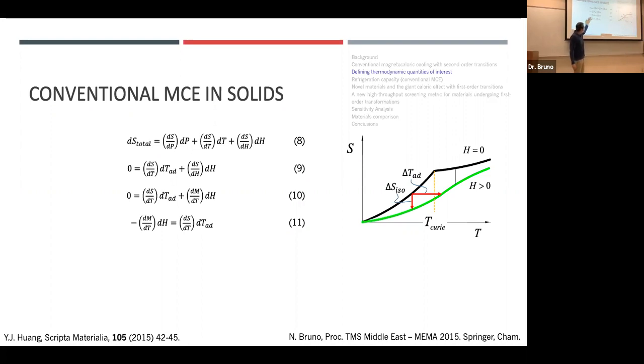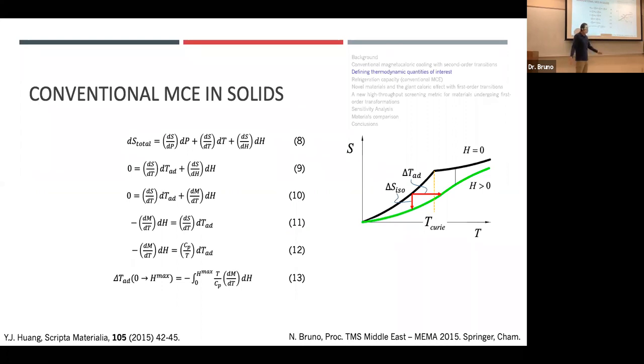We can separate it, move it to the other side of the equation, and apply the second law of thermodynamics that says dS/dT is our isobaric heat capacity divided by temperature. And we come up with this: the adiabatic temperature change equals the integral of T over Cp times dM/dT dH. Okay. And a lot of the time in literature, what you'll see is people will assume that T over Cp is independent of magnetic field, and they pop it out of the integral, and you have an approximate expression here for your adiabatic temperature change, like the thermodynamic conjugate to isothermal entropy change. All right.